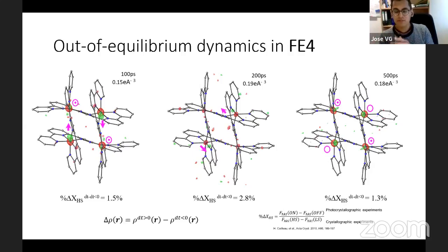This is not usually observable in monometallic materials. In monometallic materials, after light radiation, there is only one change, so the direction does not change over time. Here it is changing. The reason is that the metals are communicating. Once you excite one of these metals from low spin to high spin, this triggers a movement, which communicates to the other metals in the grid, and this passes information. When all the information is passed to the other metals, it receives a feedback, and this feedback creates this constant rearrangement in the grid.